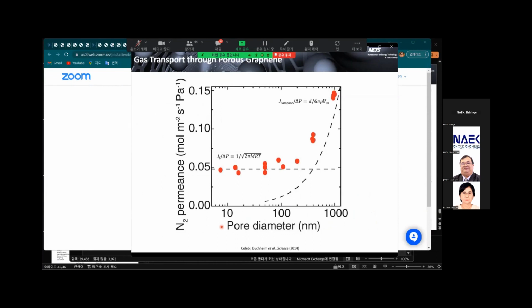The wide range of perforation capability has enabled us to explore the transport regime from free molecular to continuum viscous flows. At room temperature and 1 bar, nitrogen gas's mean free path is approximately 70 nanometers. Pores on graphene smaller than 70 nanometers show the transport characteristic of Graham's diffusion clearly, and pores much larger than 70 nanometers present asymptotic behavior nearing Sampson's flow. And in between the two regimes, our experiment provides data for gas permeation in the transition regime.